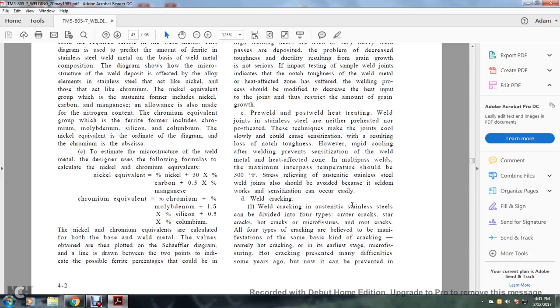C. Pre-weld and post-weld heat treatments. Weld joints in stainless steel are generally made with neither preheat nor postheat. The technique is to make joints coolly and slowly because of the sensitivity and resulting loss of notch toughness. However, rapid cooling after welding prevents sensitization of the weld metal and heat-affected zone. In multi-pass welds, maximum interpass temperature should be 300 degrees Fahrenheit. Stress relieving of austenitic stainless steel welded joints should be avoided because it seldom works and sensitization can occur easily.